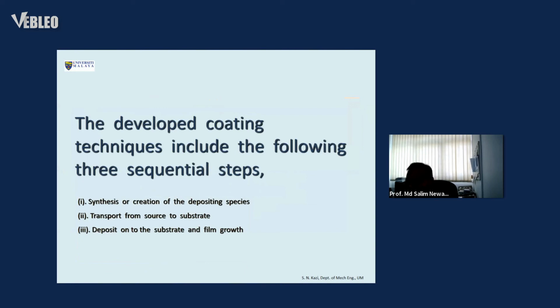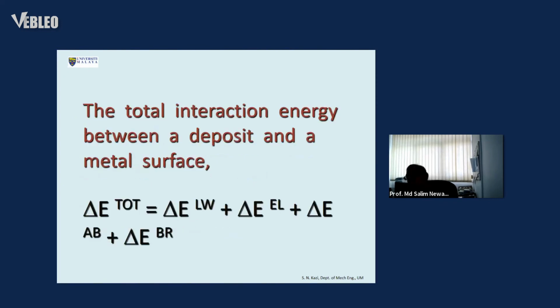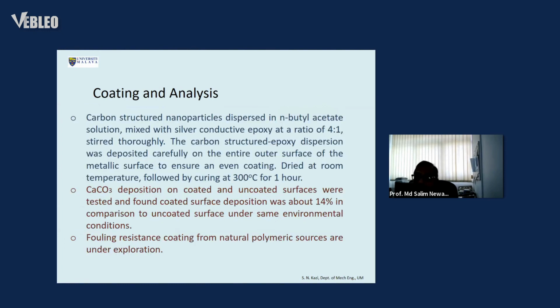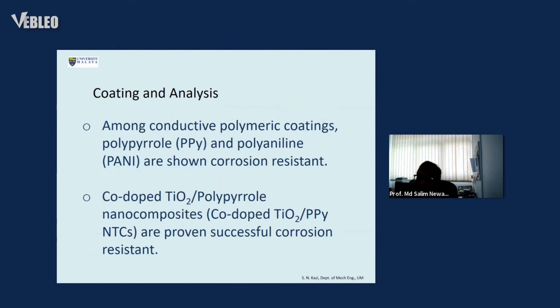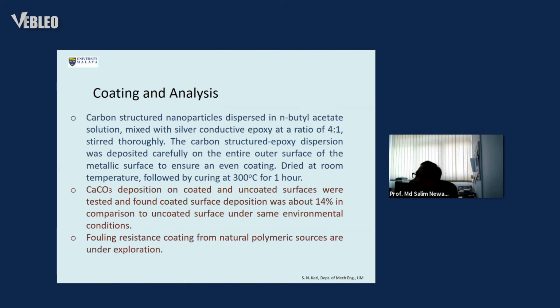Now we move on to the coatings, and we see that in many cases, the surface alteration by adding coatings or by modifying the surface by different means can also retard the rate of deposition. We find that if the total surface energy is lower, there is less deposition. If the contact angle of the surface is greater than 90, that means it is more hydrophobic in nature, so it retards the rate of deposition on the surface. In this case, different polymeric and polymer and metallic composite coatings are applied for the retardation of fouling on the surface. Some of the procedures are mentioned here.